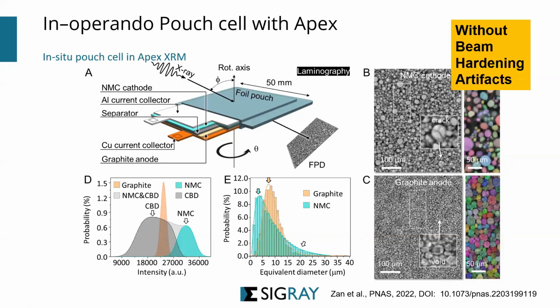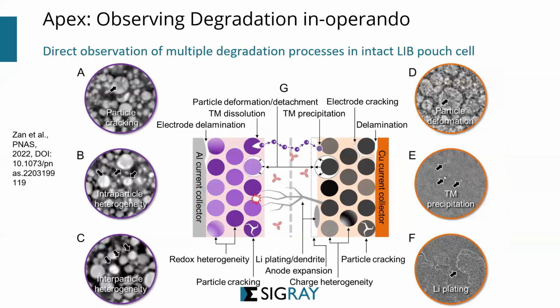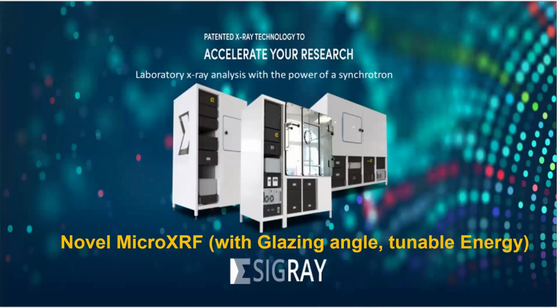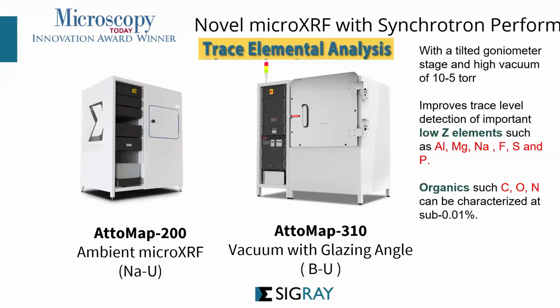So that is without beam hardening using this technique, and you can now observe the multiple degradation modes within this pouch cell battery. So the last part, with the remaining few minutes, I want to talk about the XRF, or X-ray fluorescence microscopy, because we have the ability to image elemental compositions down to a few microns spatial resolution using this technique, and it has the glazing angle in order to look at many low-Z materials.